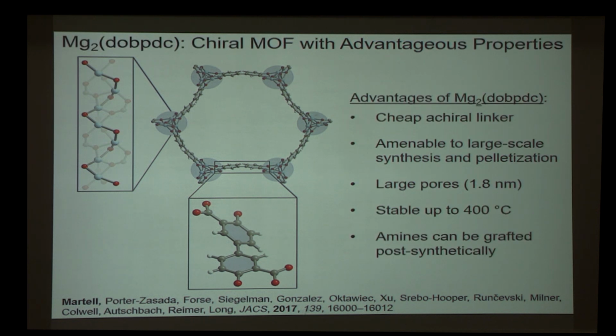And I was quite excited about this realization because this MOF has some advantageous properties for chiral separations. It's made from cheap achiral starting materials. It can be made on large scale and turned into pellets. It has large pores on the order of 1.8 nanometers. And it is stable up to 400 degrees Celsius. And perhaps most importantly, as I showed in the first part of this section, amines can be grafted post-synthetically to this material. So we can think about precisely tailoring this chiral three-dimensional cavity to bind to specific guest molecules of interest.